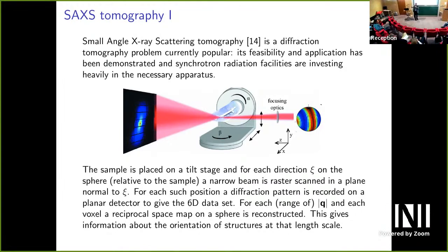So you can make that suit your camera for measuring it. But the deflection angle is small, and it means you can take the small angle, sine theta, approximation. Anyway, so they actually do this, with a sample that's not crystalline, but has some kind of spatial orientation on the relevant length scale that you're measuring.